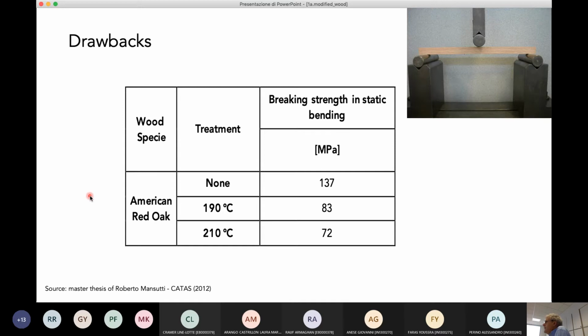This is again the thesis of Roberto, showing us some results of the mechanical tests, and you see that the bending strength is dramatically reduced, around the half for wood already treated at 210 degrees. So it's a strong decay of the mechanical properties of this type of wood.